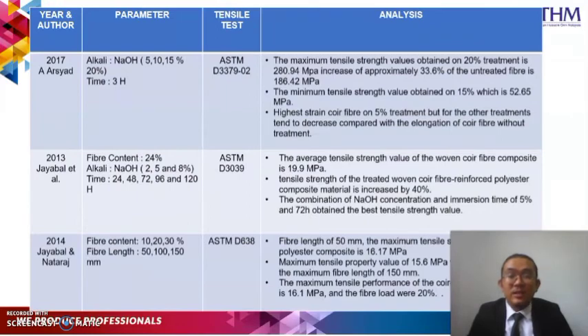In 2017, A. Arsyad found that the maximum tensile strength value was obtained on 20% treatment and the minimum tensile strength value was obtained on 15%, which is 52.65 MPa. The highest strain of coir fiber was on 5% treatment, but the other treatments tend to decrease compared with the elongation of coir fiber without treatment.